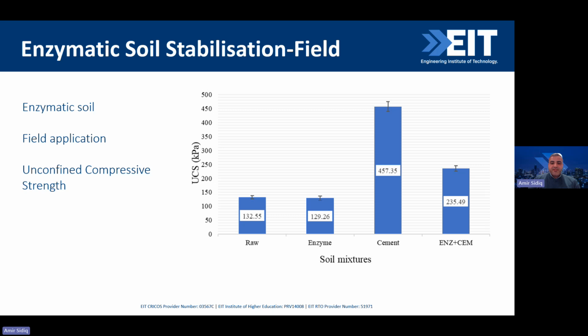Then we have the enzyme and cement together. Now, the question here could be why enzyme is added to cement to reduce the strength, where the strength is actually pretty high. That is exactly right. However, when we're dealing with different environmental conditions, the protection of the enzyme, we obtain this information, this analysis, quite deep analysis from the laboratory. Now we need to protect our clay against different environmental conditions. So we use enzyme in that case.